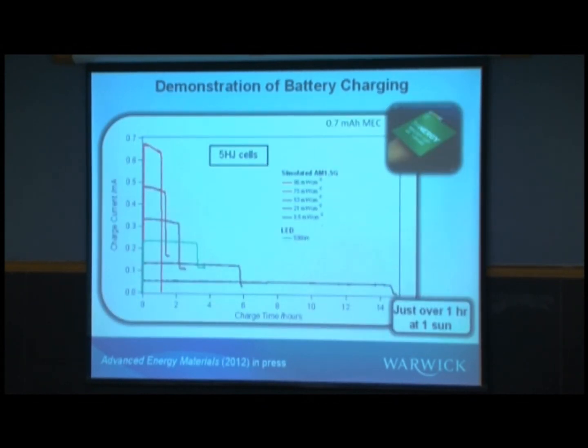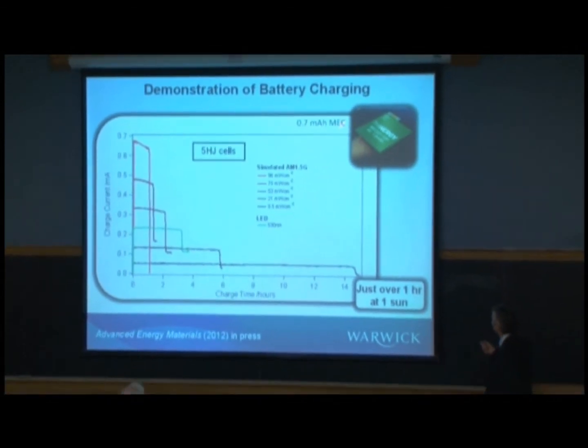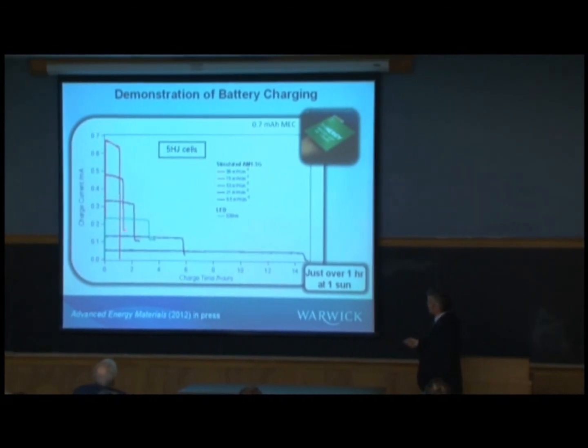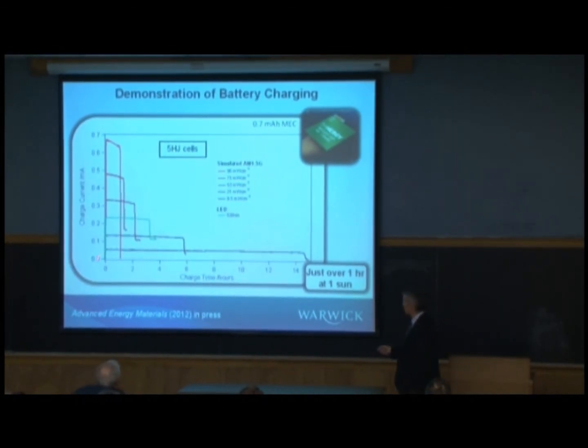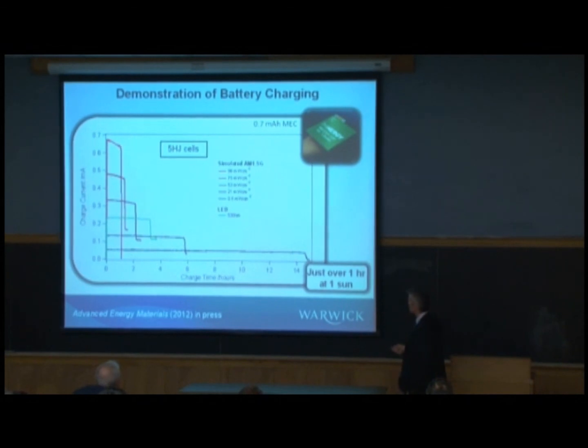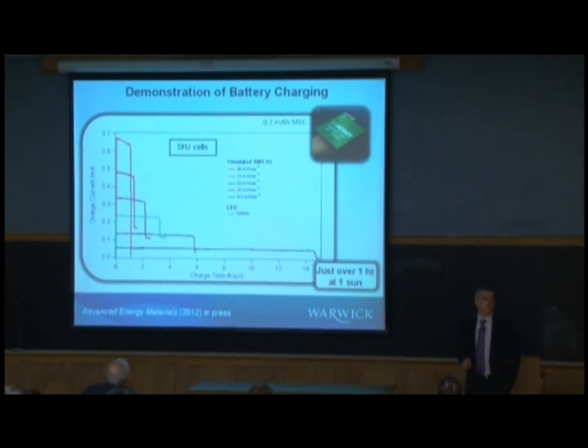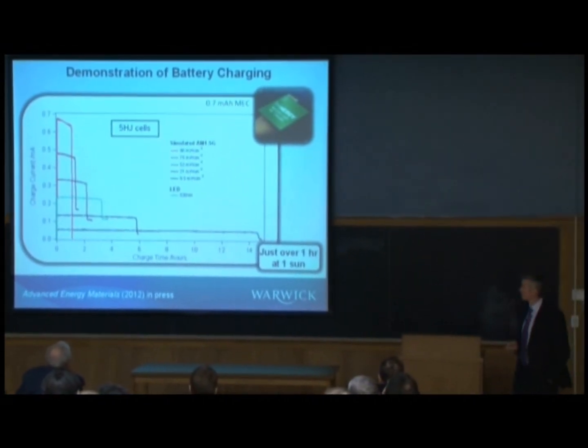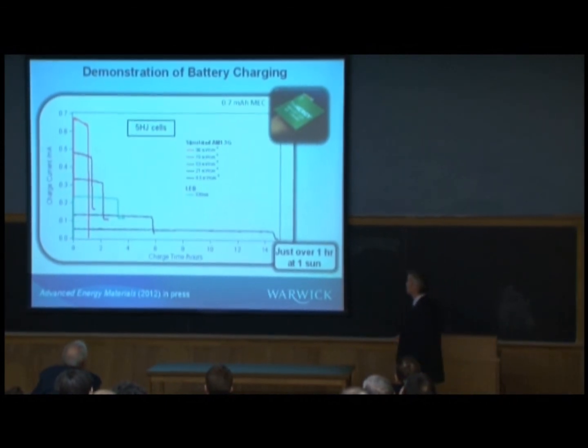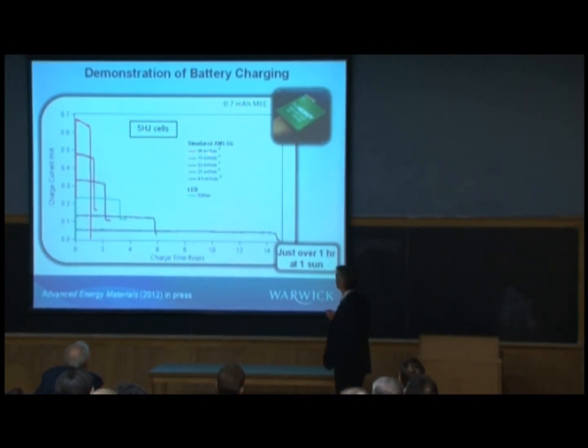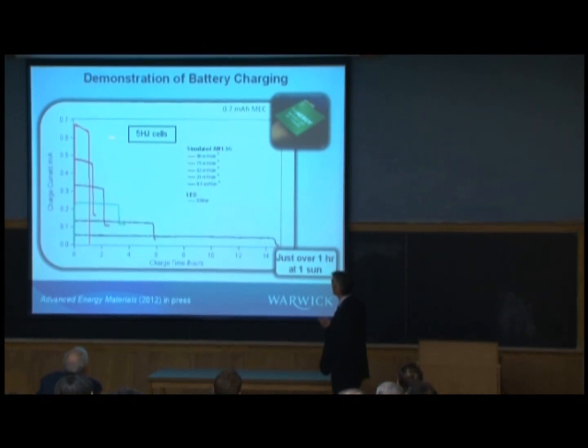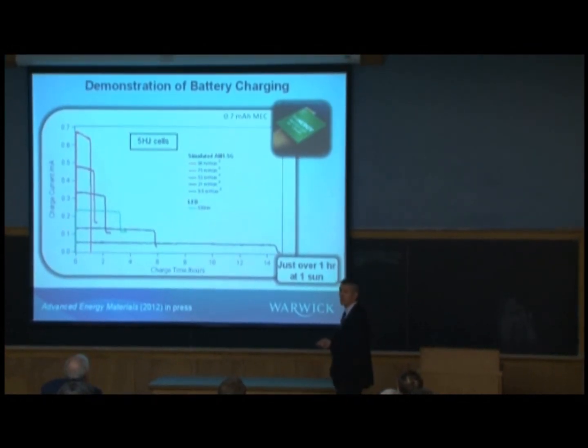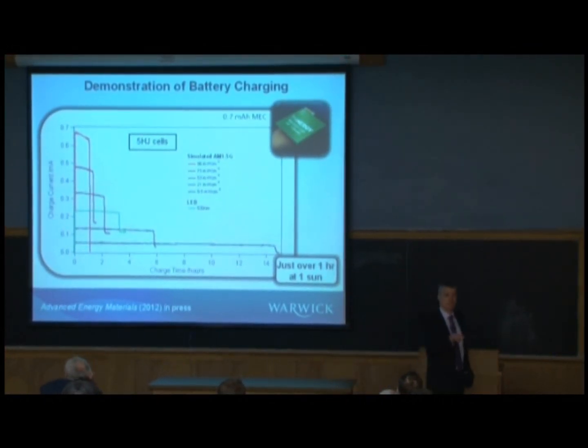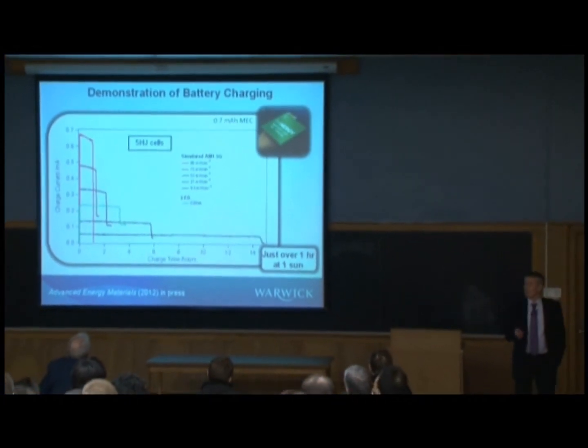So just to show it works, this was a simple lab-type demonstration, taking a 0.7 milliamp-hour battery. Shown here is the charge current as a function of charge time, for a 5 heterojunction device, which gives us this high voltage, the voltage necessary to charge. And what you see is that under 1 sun, under 100 milliwatts per square centimeter, charging is complete in 1 hour. So if you put your cell outside, it would be complete in an hour.